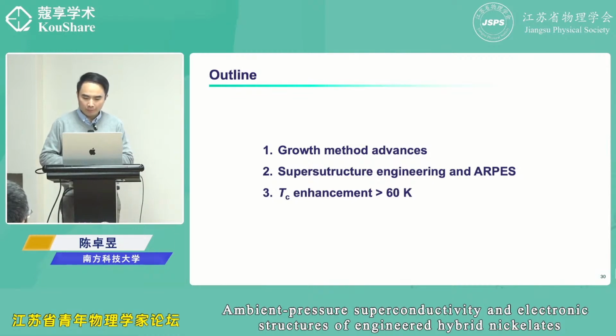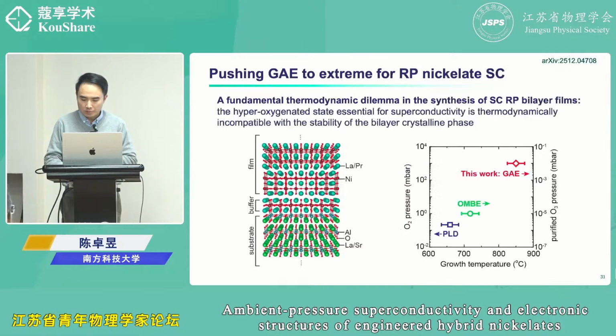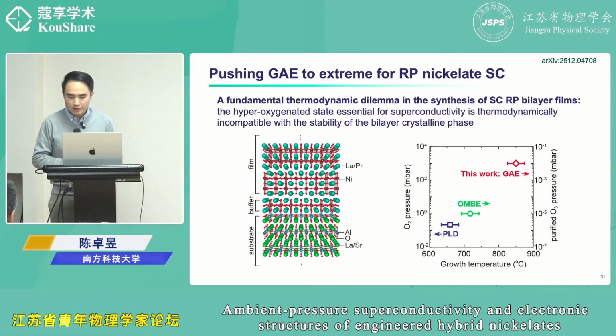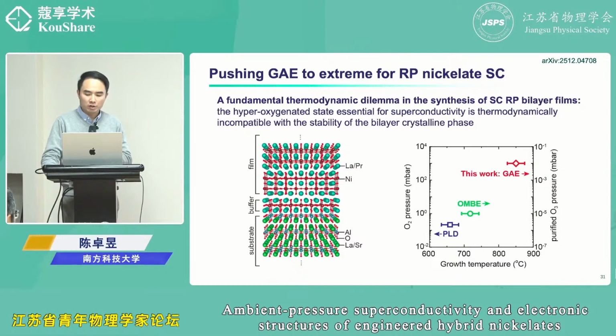Right. So we come to the last part: how to get this 60 Kelvin enhancement. In our understanding, this is very related to a fundamental thermodynamic dilemma in the synthesis of these superconducting Ruddlesden-Popper bilayer films. The hyperoxygenated state that's essential for superconductivity is actually thermodynamically incompatible with the stability of the bilayer crystalline phase.